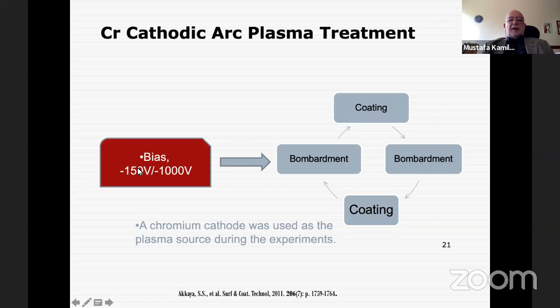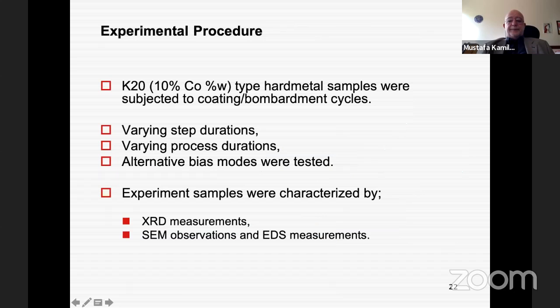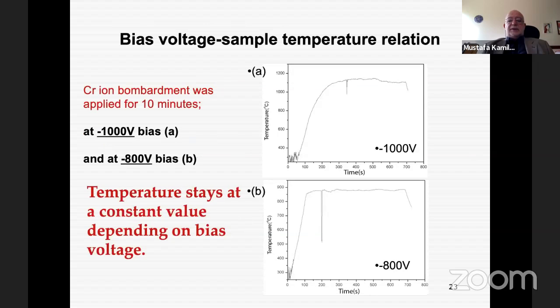In this case, when we apply 150 volt bias, we deposit. When we apply 1000 volt bias, we heat the sample. So we coat, and bombard in this manner. We made a chromium coating, bombarded for allowing the diffusion to take place. And for this purpose, we use a chromium cathode and cathodic arc chromium plasma. And these are the samples that we are using. We used a 10% cobalt containing sample.